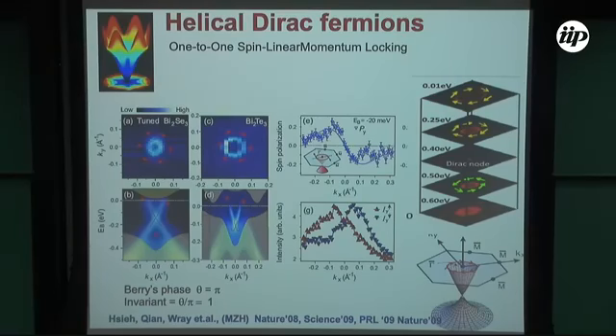This is the simplest example that will give you a feel for what it is. So what we are doing here, this is one of the first 3D topological insulators, bismuth selenide and telluride. If you look at the bulk band structure, you see it's superimposed on the surface. You see there is a linear crossing. And if you just look at the Fermi surface, there is a single Fermi surface in the Brillouin zone. And each point on the Fermi surface is spin polarized.